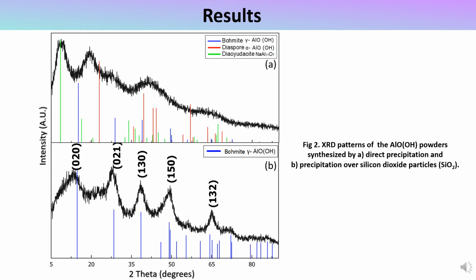On the other hand, in figure 2b, we can observe the diffraction patterns for precipitation over silicon dioxide particles. We observed only characteristic planes of gamma boehmite. We conclude that, using the silicon oxide particles as nucleus, we had a great control of the phase. In addition, the boehmite is directly transformed to aluminum oxide.